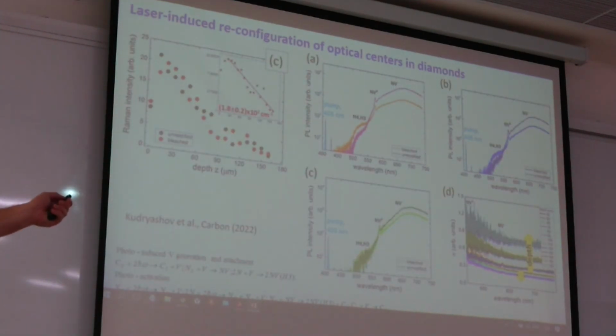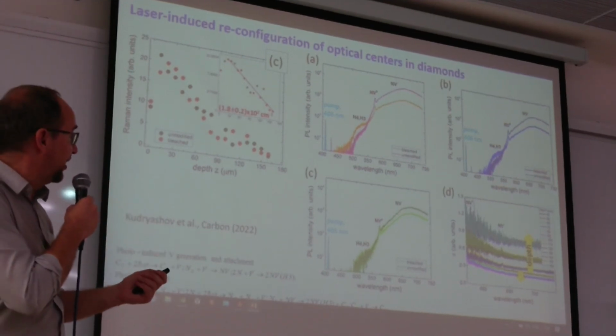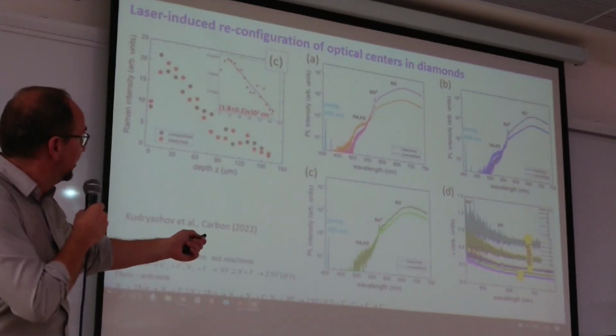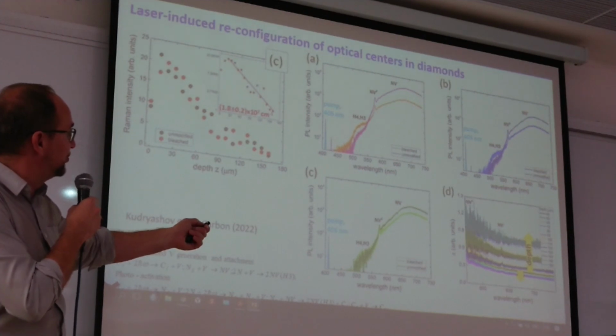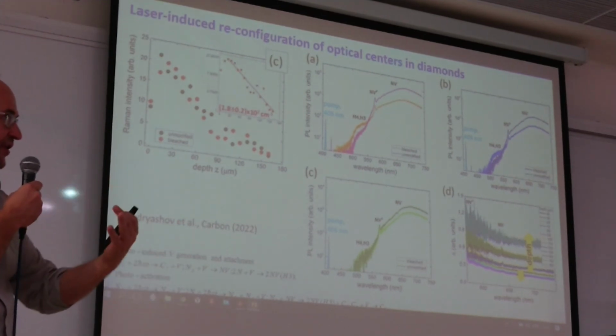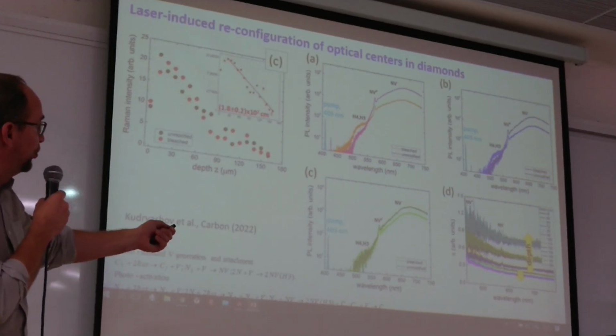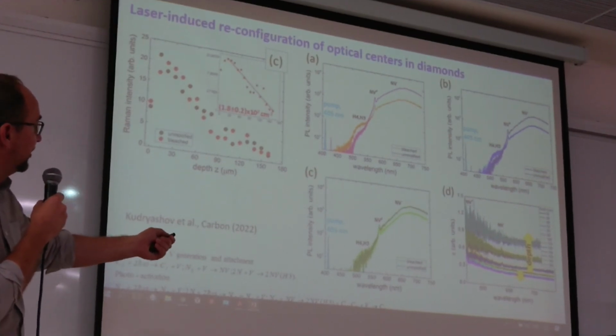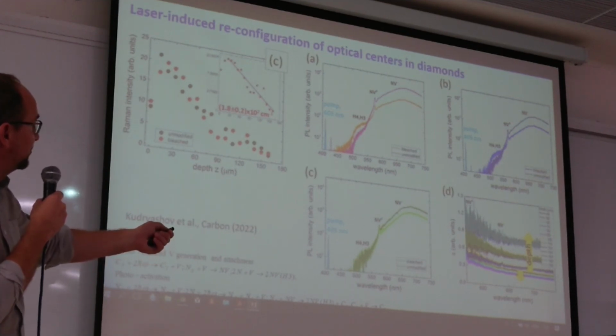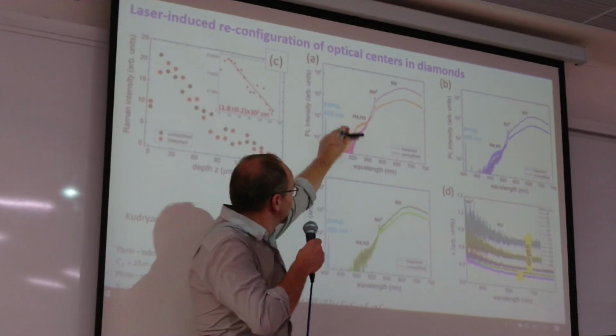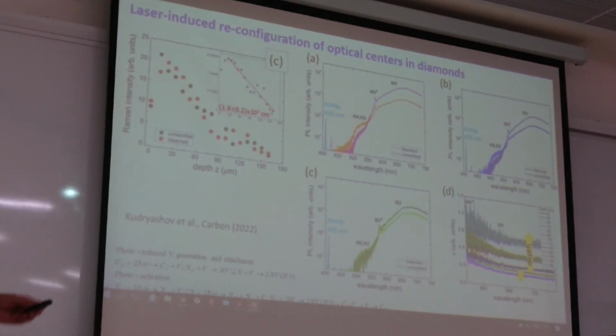Diamond is not damaged because we can see the Raman in diamonds, reference spectra, and the modified regions show the same Raman intensities, but the change of color, the bleaching, results from a decrease of NV centers, which are absorbing in the red region, and an increase of blue emitting centers. You can see here the unmodified material changes to modified, so there is an increase of blue emitting centers and a decrease of red-green emitting centers.